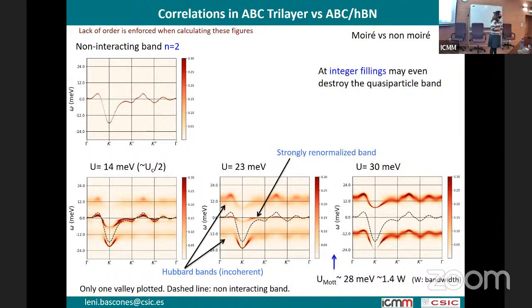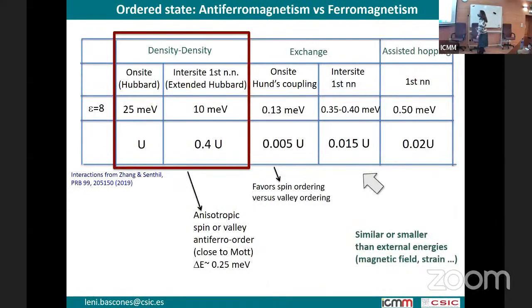So if U is large enough, the density of states that was driving ferromagnetism in the trilayer will not be able to do so, because it has even disappeared. And in any case, even at smaller values of U, one expects that these bands change. So the question is, how small is this U in the real experiment? That is the issue. The other question is, from a Mott perspective, if one finds ferromagnetism instead of antiferromagnetism, is this telling us something about the nature of these states?